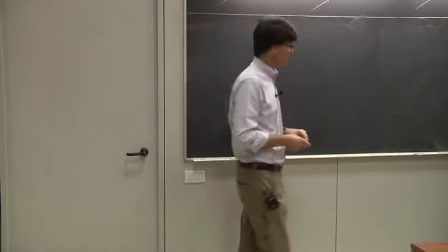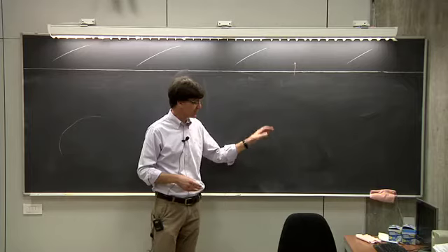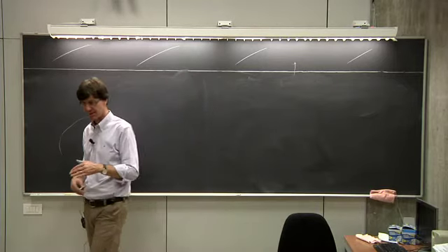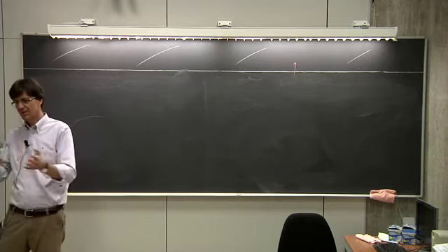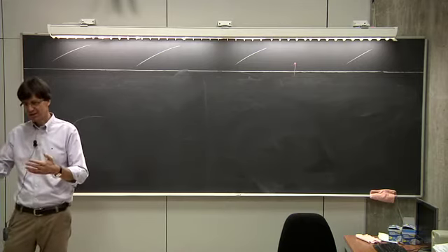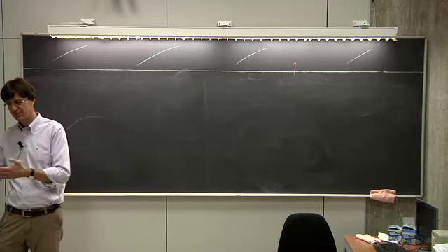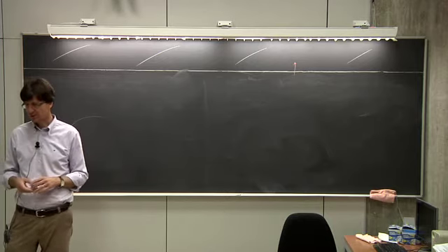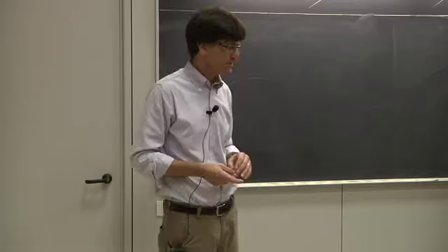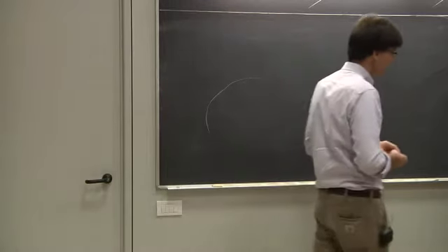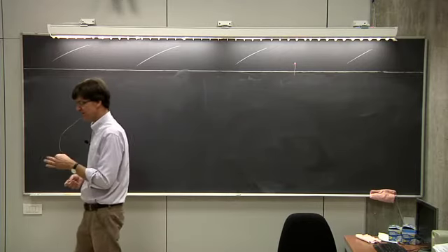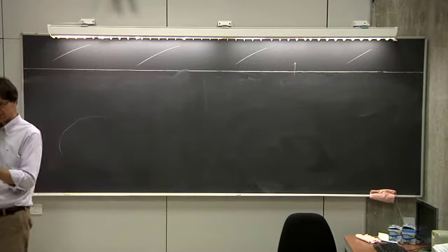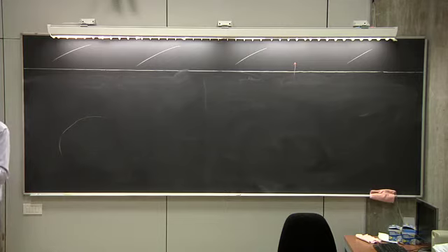Why do we choose only X-rays? It's only X-rays because you want to look at core states. And as soon as you go beyond oxygen, let's say, the 1s state goes deeper and deeper, so you're talking about kilo electron volts. You want core states because they are very localized in space, so you can easily understand the electrostatics of a core state because it's like having a point charge.